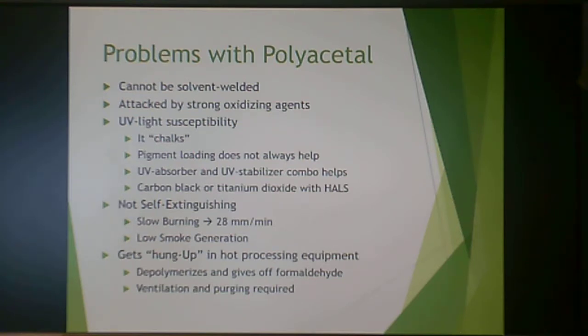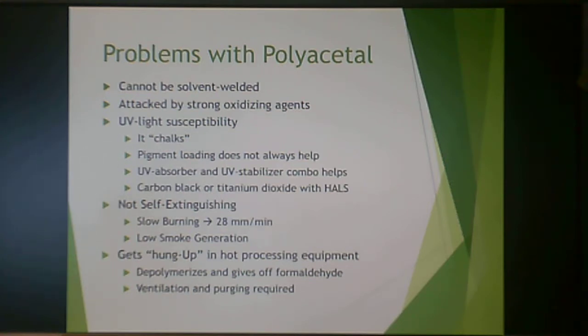A major processing concern is that polyacetal can get hung up in hot processing equipment. When it does, it zips and depolymerizes to give off formaldehyde. This means any area where polyacetal is processed must be well ventilated, and equipment must be purged effectively, because reheating above processing temperature will cause zipping and formaldehyde release.